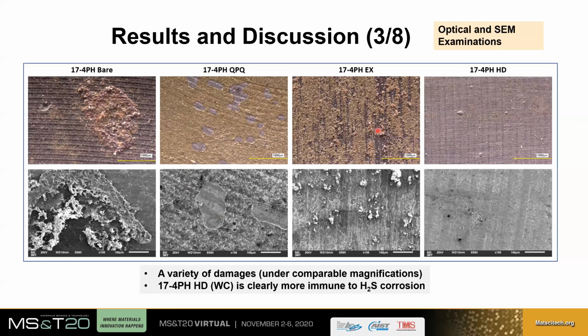When we look at this low temperature nitriding, we also have this golden appearance. We don't see this layer flaking off, or at least not to the same extent, and perhaps not within 2 weeks. Please remember, this picture applies to test number 1 only, and test number 1 was only 2 weeks. If you were to look at 1 month, 2 months, and of course continue this test, there is no doubt corrosion will proceed, and eventually we would probably find something very similar to what we saw on the left, where essentially the surface treatment, upon being corroded, falls off. Okay. On the left side, we essentially see just a bit of pitting and deposition.